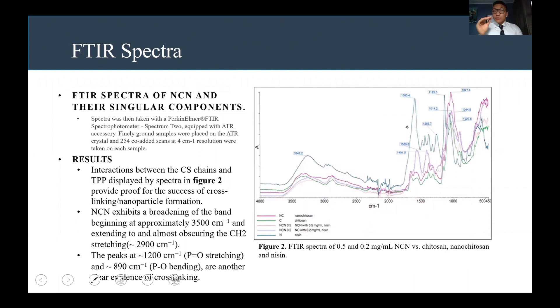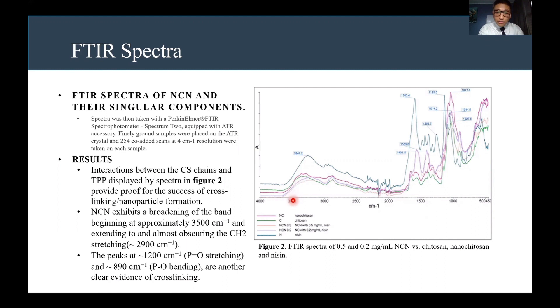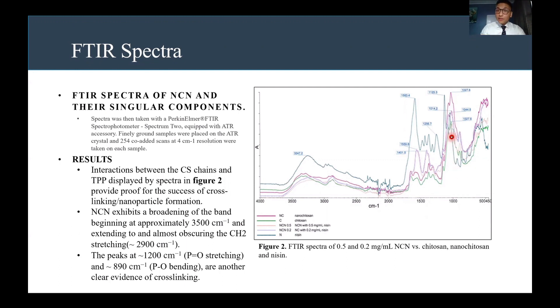We also put our solid nanoparticle samples through FTIR spectra. The first run compared NCN — nisin encapsulated in chitosan nanoparticles — to their singular components of nisin, chitosan, and nano-chitosan. Analysis of Figure 2 showed that interaction between chitosan chains and TPP provides proof of successful cross-linking and nanoparticle formation. Around the 3500 range, we see a broadening extending to the 2900 range, which obscures the CH2 stretching. We also see peaks at 1200 and 890 reciprocal centimeters in the nanoparticles, which are further clear evidence of cross-linking.